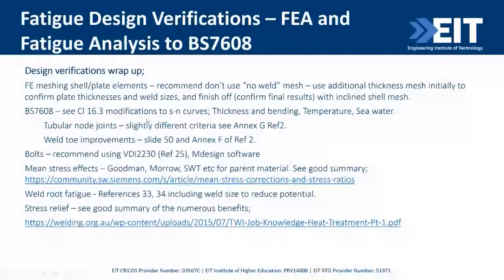Okay, to wrap that up then, read the standard fully. Don't use the no-weld mesh. If you're going to model a ship structure, you're not going to model it in solids. You haven't got time or disk capacity. If you want to do that mesh initially, okay, then finish it off with the additional thickness mesh method and/or the inclined shell mesh. But for a stereo fan, for a vibrating screen, I wouldn't use the no-weld mesh. I'd use straight into additional thickness or straight into inclined